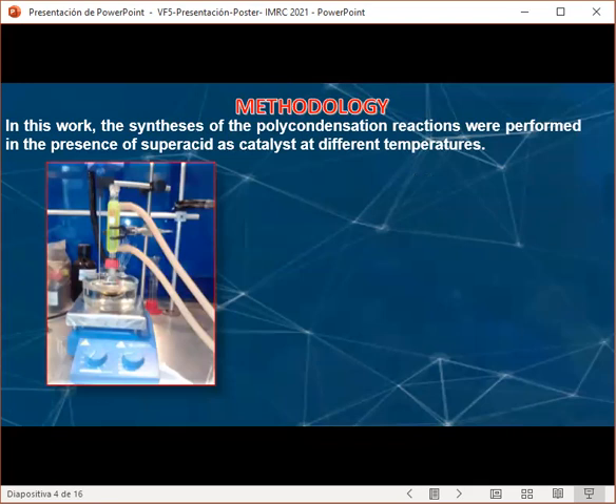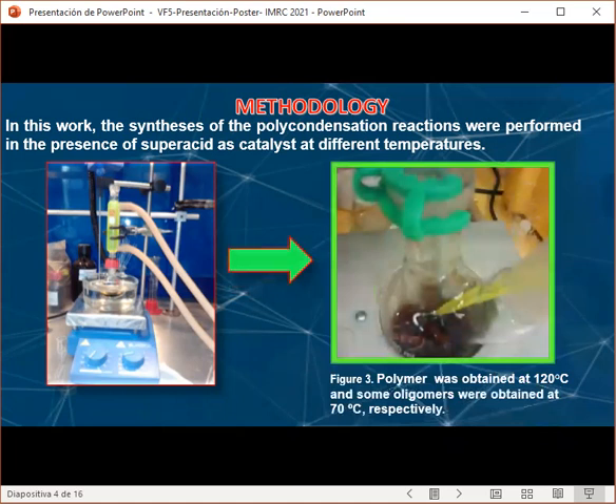Next, in this slide, the methodology in this work: the polycondensation reactions were performed in the presence of the superacid as a catalyst at different temperatures. You can see in Figure 3 the polymer in the form of resin. It was obtained at 120 degrees, and some oligomers were obtained at 70 degrees, respectively.